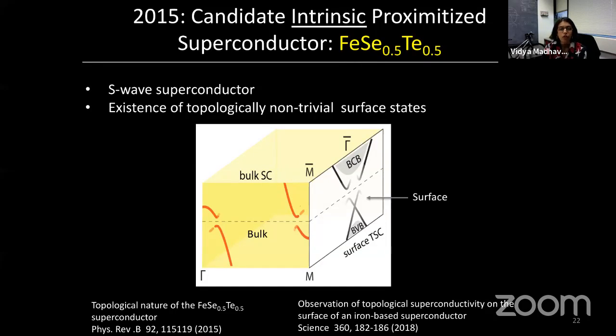However, what was shown in 2015 is that one of the bands of this material show band inversion. And band inversion is what you need to make the material topologically non-trivial. So if you have band inversion for just one of the bands at the gamma point, then you should expect these Dirac surface states. So you should see these Dirac surface states on the surface of this material.